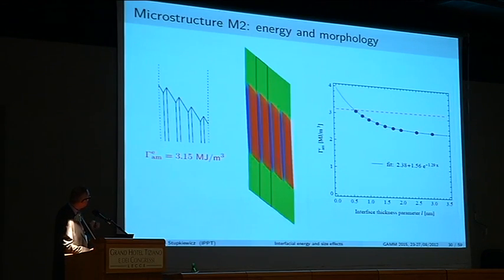If we look at the energies, this is the result of our sharp interface modeling by shape optimization. And this is the result of phase field modeling. And here we see that it's not too good. I mean, the result depends on the characteristic parameter for the interface thickness. Of course, if you make your interface thinner, then you resolve the stress concentration with higher accuracy, and that's the result. But the order is more or less okay.